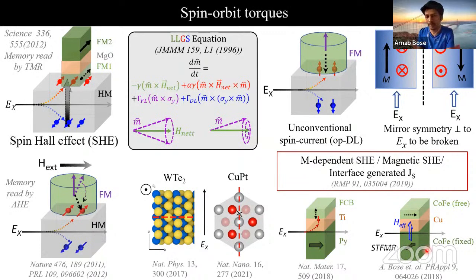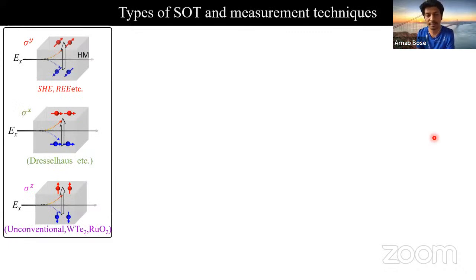However, there could be some issues with a ferromagnet as a source of such unconventional torques, because the magnetization can be influenced by external field perturbation. So we may need robustness like a heavy metal and at the same time magnetic ordering. Simultaneously it can be fulfilled if we have an anti-ferromagnet, which I'll discuss in the next part of my talk. So now let's have a look at what are the different types of spin current and spin torques we can get from a system and how do we experimentally measure it.